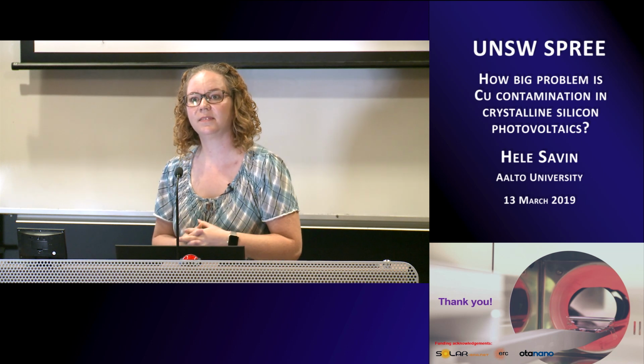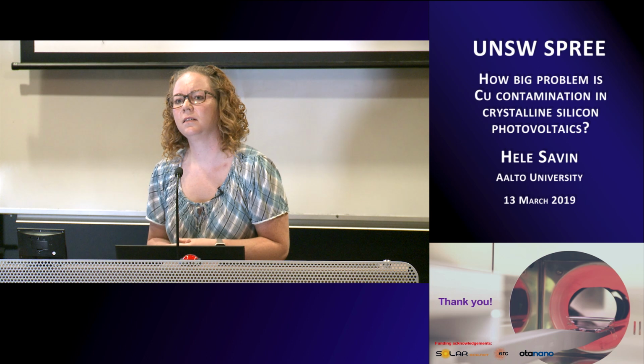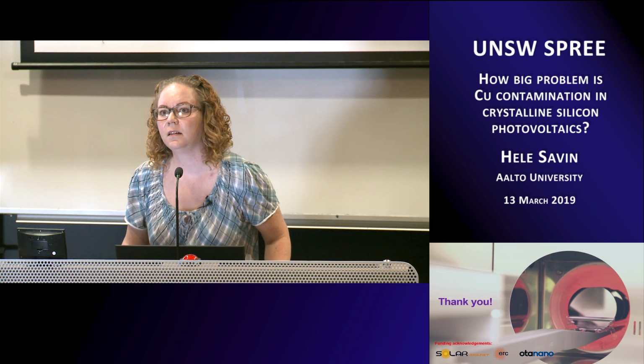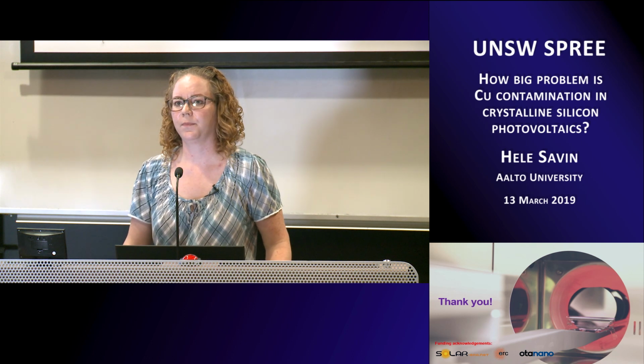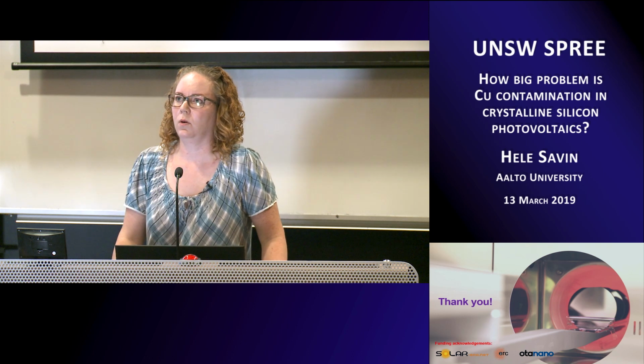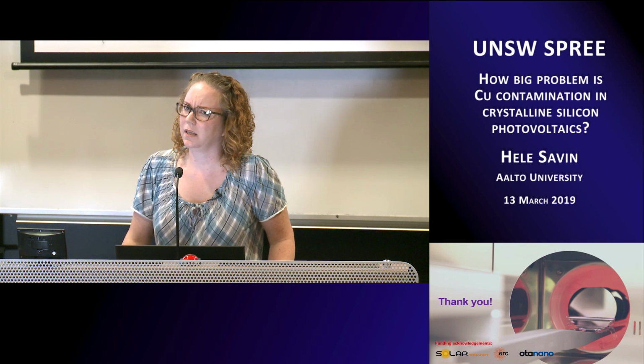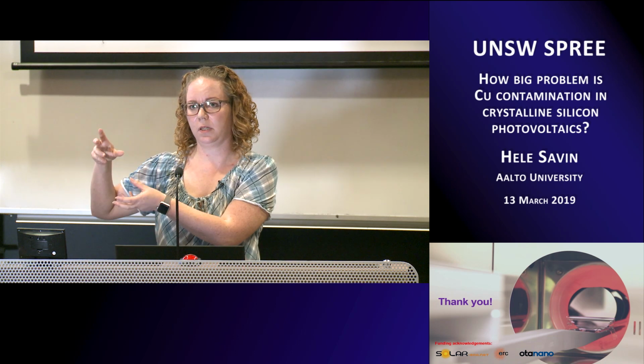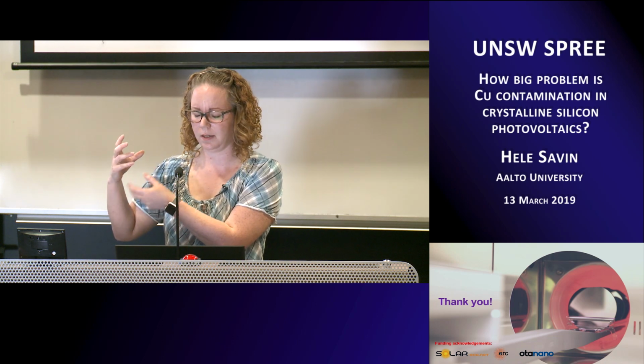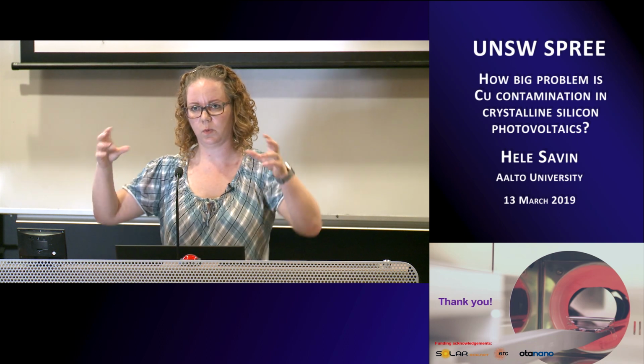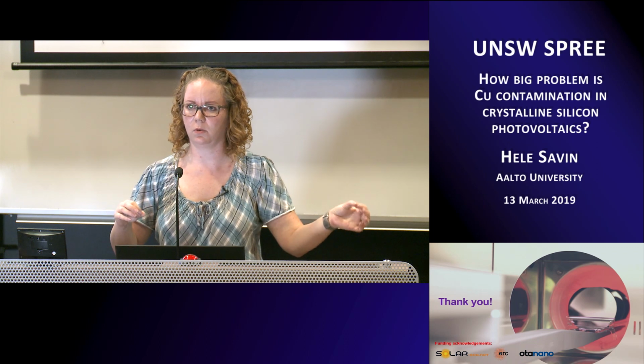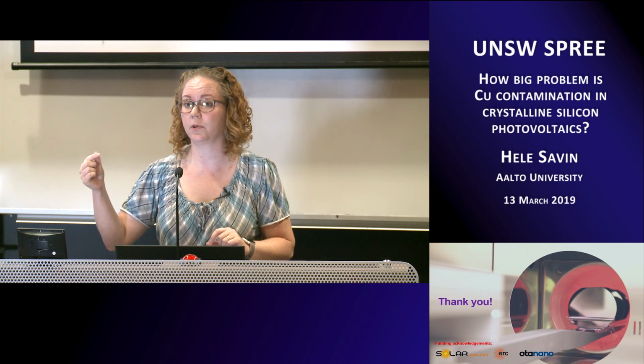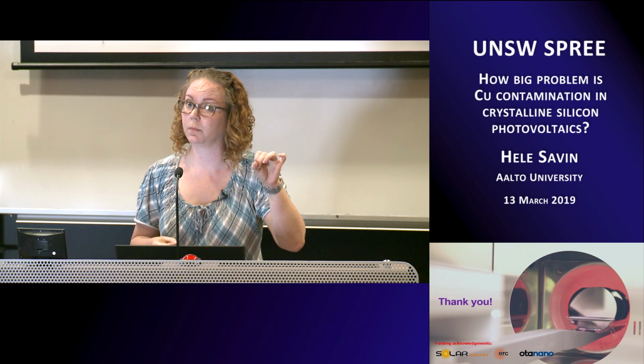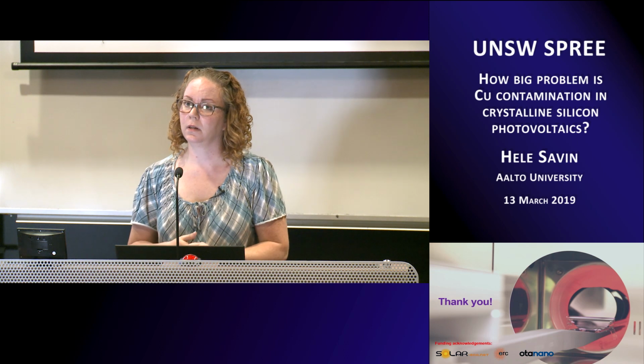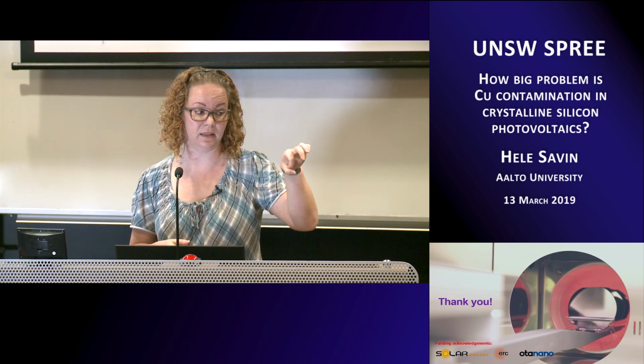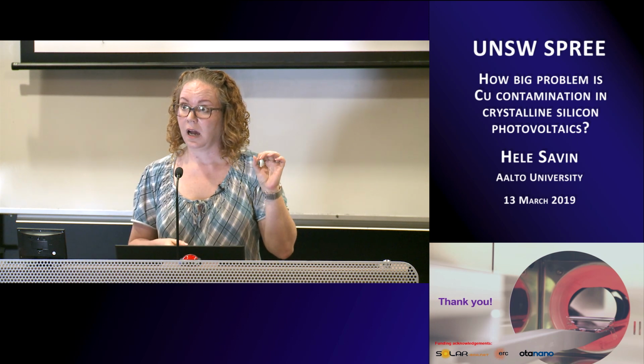Thanks for the talk, it's really nice. I have a few questions. With respect to that particular question, do you know the concentration more or less of these different spots? So what's the range of copper that you've been using? Parts per billion, I think. We have a specific high purity liquid of copper sulfate, and we dilute it with a certain amount so that we can count how many copper atoms we have. And when you know the volume of your droplet, you know exactly the total amount of copper atoms in that droplet. So you can quantitatively count on that.